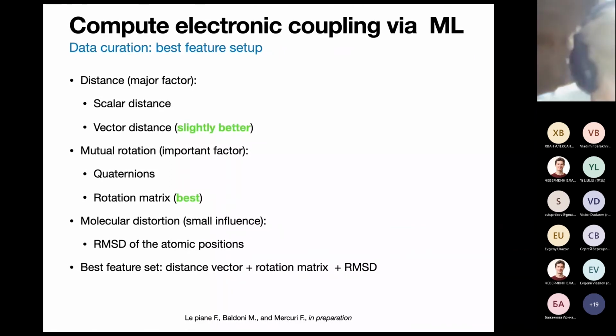The mutual rotation of the 2 molecules in the pair can be represented with quaternions or with the rotation matrix, and we found that the rotation matrix representation is the best one. The molecular distortion, which has a small influence but is still important, is represented by RMSD, the root mean square deviation of the atomic positions of the real molecule, I mean the molecule in the real aggregate, compared to the molecule in its idealized geometry, optimized in vacuum. So our best feature set is the distance vector plus the rotation matrix plus the RMSD.